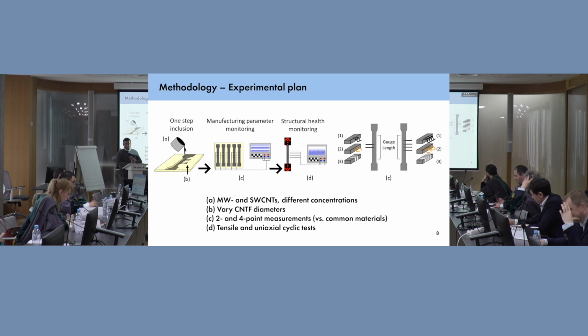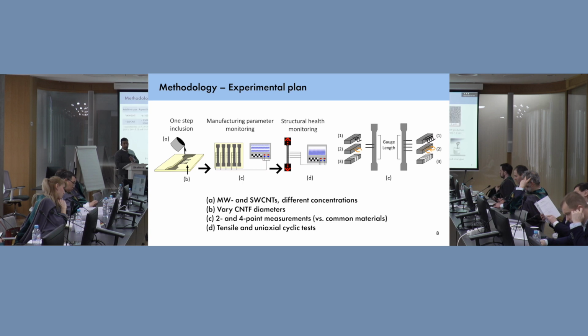And just to show how these electrodes go into the length, into the volume of our gauge length, we just put some pictures up. Besides this, to answer the questions that we had before, we vary CNTF diameters to see if these parameters have any effect. We conduct measurements during manufacturing, monitoring by both 2 and 4 point, and then our mechanical loading was tensile and uniaxial cyclic tensile tests, just to see where we get.